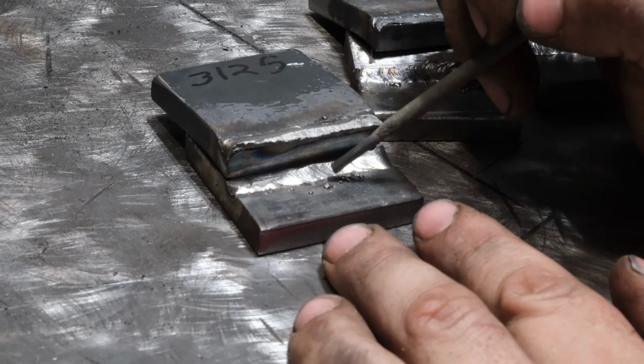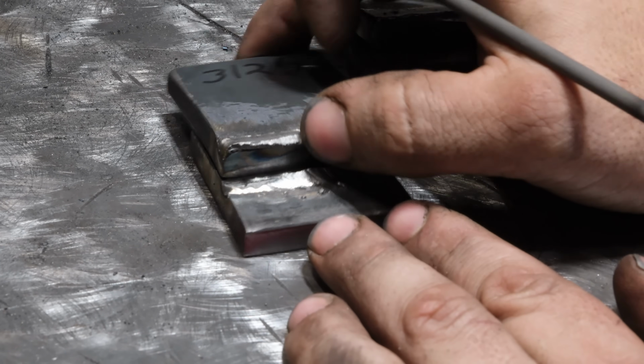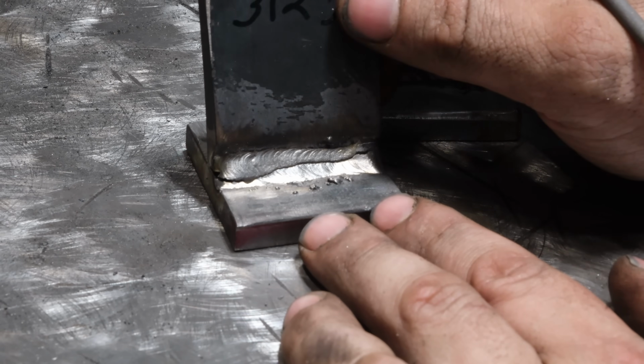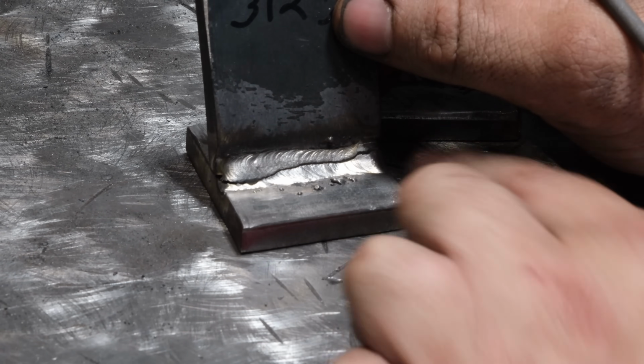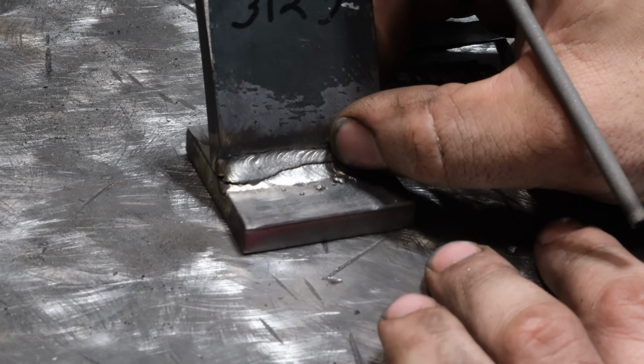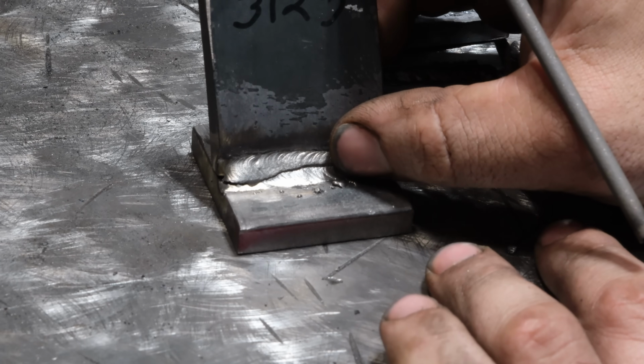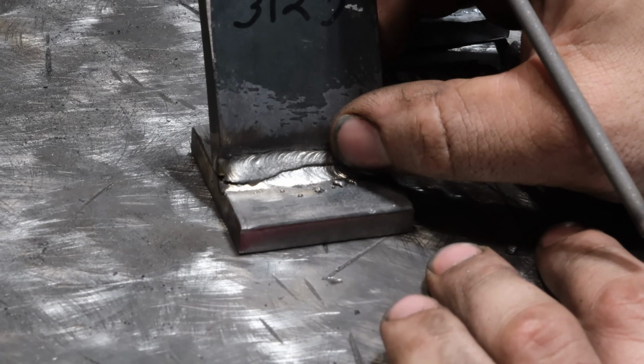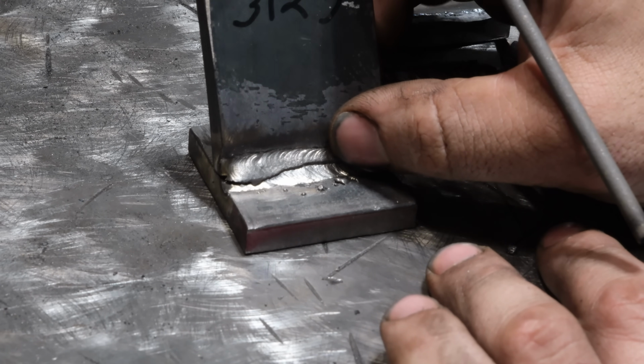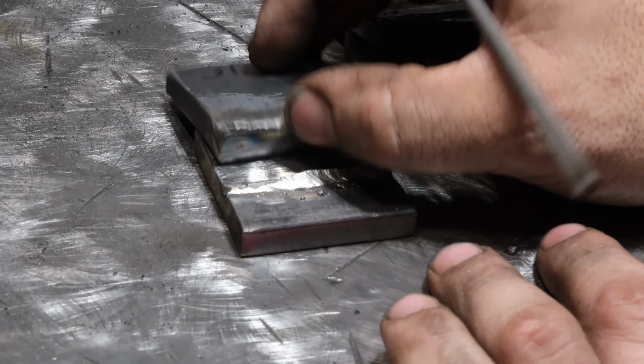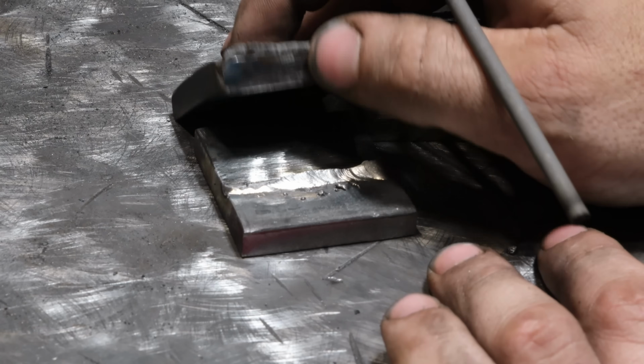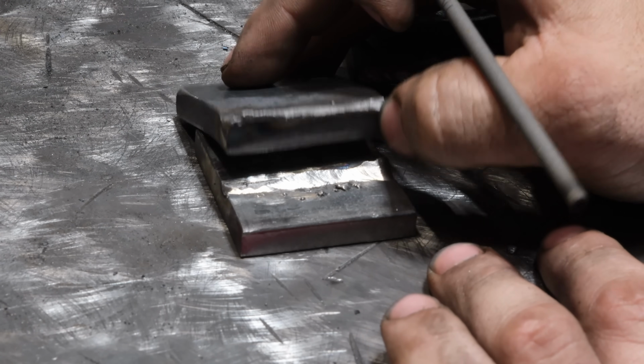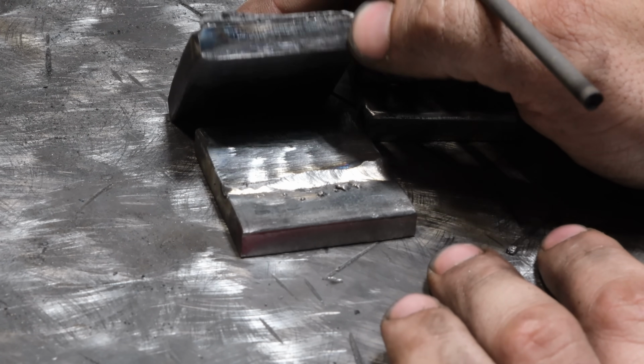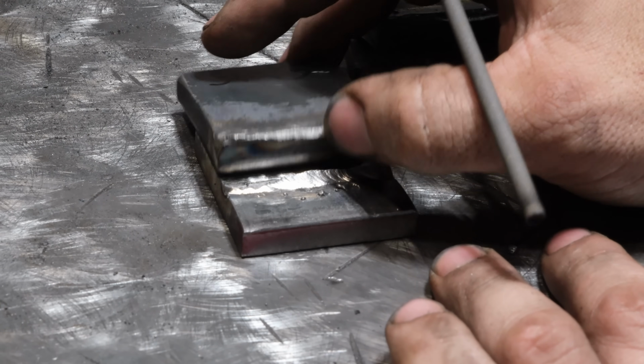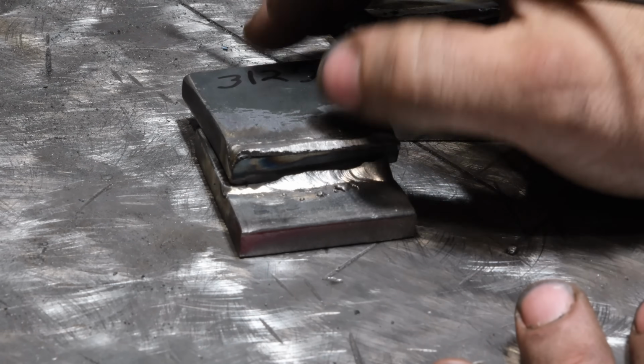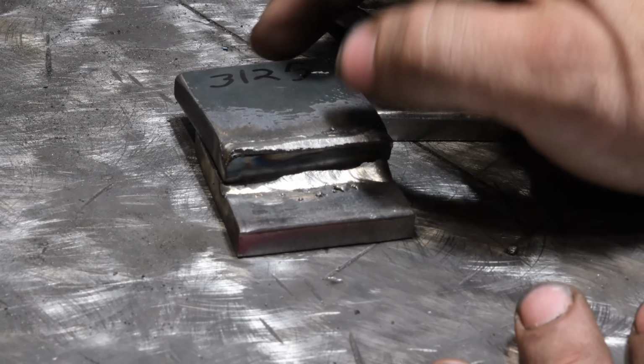When you combine those two things and do a single pass weld, there simply isn't a whole lot of weld material to hold this. And you can see how wide and flat that spread it out. Maybe if I would have done 2 more passes, it would have held together better. But again, we're just looking at single passes here. So I wouldn't anticipate anything more than what happened here. Penetration, the whole original edge of the plate is still there. It had 0 penetration on this. And had I ran any more amperage, it just would have had even worse arc blow.